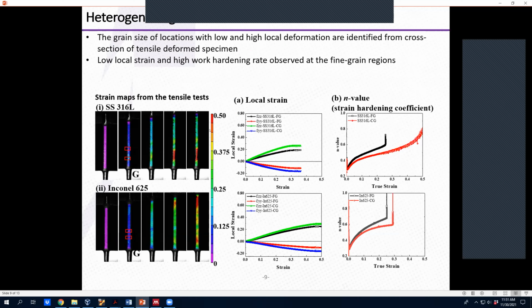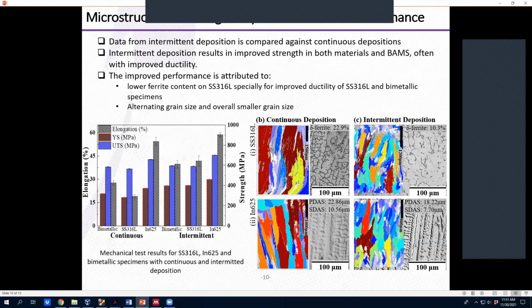After figuring out the deformation mechanisms, we also compared the mechanical performance with the continuous deposition, or continuous columnar growth, regions. For both materials, with the intermittent deposition strategy, or the alternating grain size, we achieved improved mechanical performance in all cases compared to columnar grain growth cases. We attribute this improvement to the change in microstructural features, and also to the grain size heterogeneity, or the overall smaller grain size, with the periodically alternating grain size in our intermittent deposition strategy.